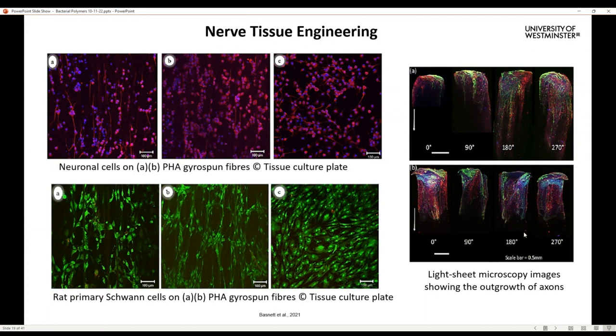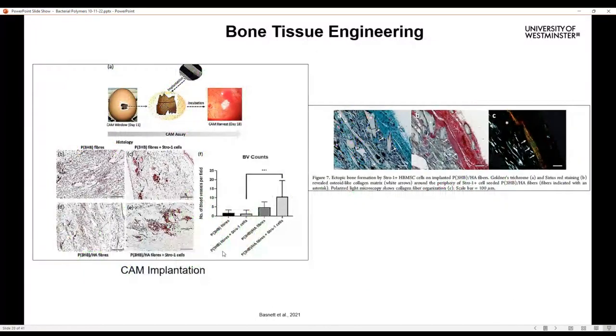If you look at this image, C is basically cells grown on a two-dimensional flat plastic surface, whereas A and B are cells that were seeded on the bacterial polymer fibers. And you can see from the pictures here that they followed the fibers and grew in a very uniform, guided manner, which is very important for the function of these cells and tissues.